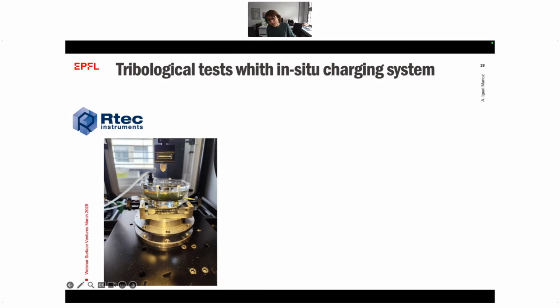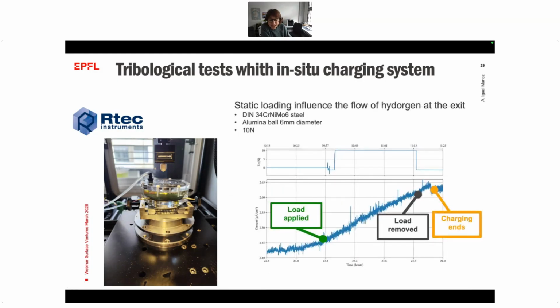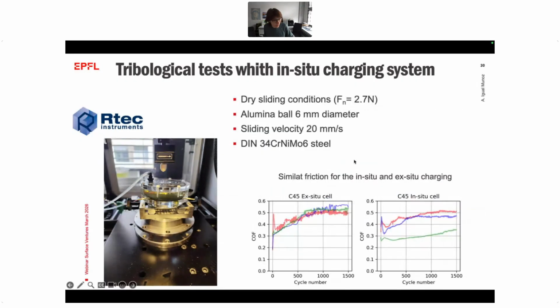But then the permeation cell we can place inside a tribometer, and this is what we did with Rtec. Then basically we can, for example, put our permeation cell here and have a look at the current, which is proportional to the hydrogen load. We apply the load, and because of the stress distribution within the material, we change the flow rate of the hydrogen through the steel. This is just by static loading. We don't wear. So the static loading, the generation of this stress field, influences the flow of hydrogen at the exit. And now we wear.